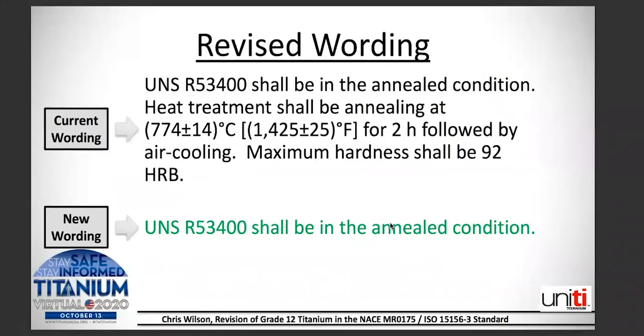So the revised wording that the project was undertaking was basically to remove the entire current wording requirements and streamline that. The new wording will be: UNS R53400 shall be in the annealed condition. As you can see, there are no heat treatment requirements, no specifications on a specific annealing cycle, and no requirement for hardness.